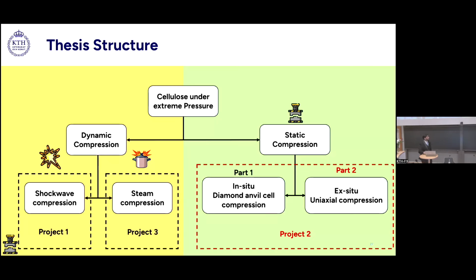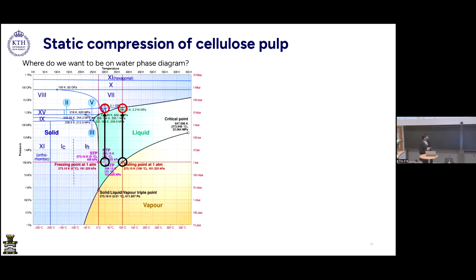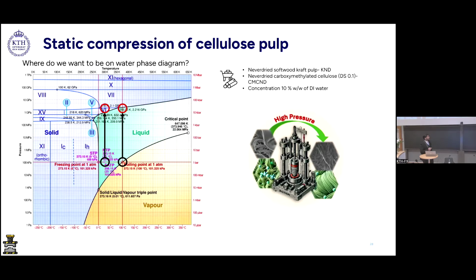So moving on to part 2, where we did the ex-situ uniaxial compression of the samples. Where we wanted to be in the water phase diagram was exactly in a similar regime to what we did in the in-situ experiment, except we also wanted to explore the high temperature regime in the same pressure area. The material we used is very similar to that of the first experiment: never-dried kraft pulp and never-dried carboxymethylated pulp at roughly 10% concentration. The experimental philosophy was that we take a bulk amount of sample and compress it in a uniaxial press. After the compression, we take the sample out and do some average measurements, so that we can have a better idea of how the material is changing over time.